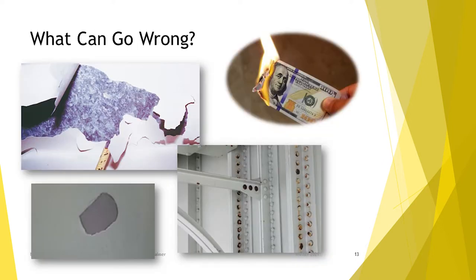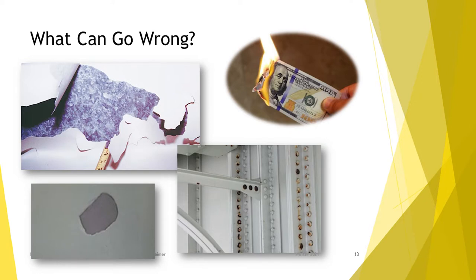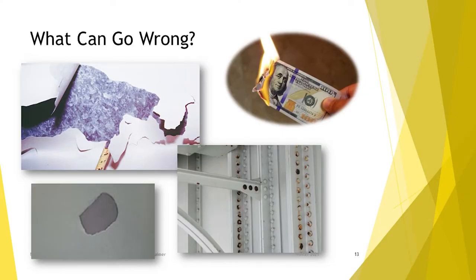So why isn't everybody using it? A couple of things stop people from using this system. It's been around for a long time, but it's more expensive, so you have the life cycle cost argument to make — spend more money now to save it in the future. There are some high-profile failures; everybody's probably seen paint peeling off a galvanized surface, and that can happen quickly if the process isn't done right. There are also projects where a fancy coating system was applied alongside black steel bolts that only got a coat of paint, resulting in a black and white speckled bridge. If things go wrong early on, it takes the wind out of the sails of spending more money upfront. The idea was to put material together that helped folks make the life cycle cost argument and avoid the mistakes that cause that immediate kind of failure.